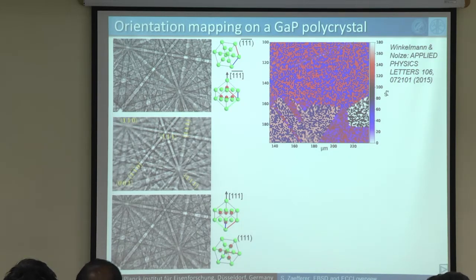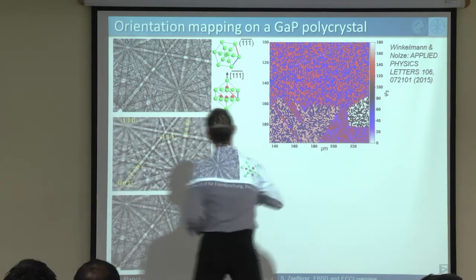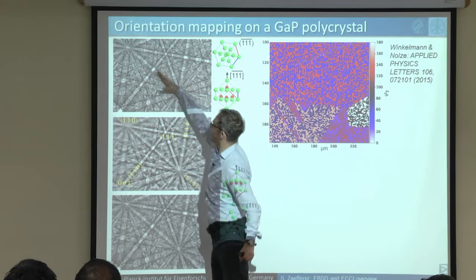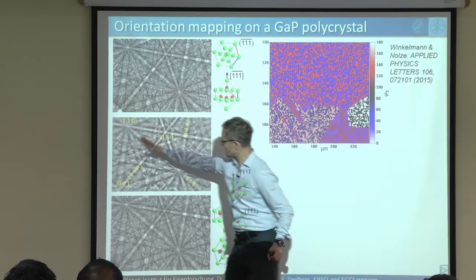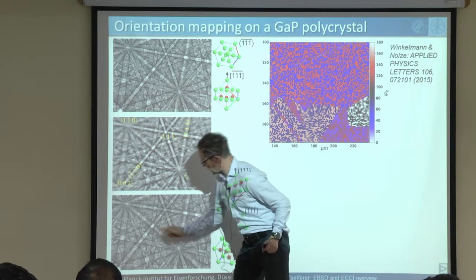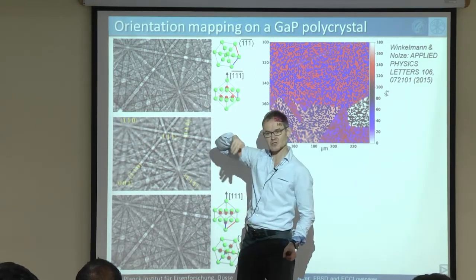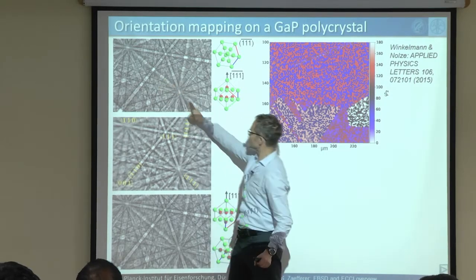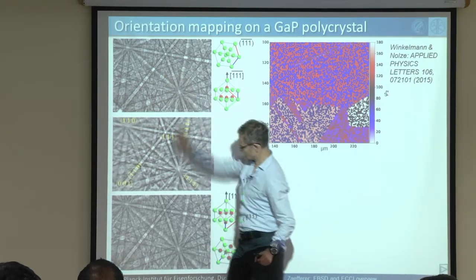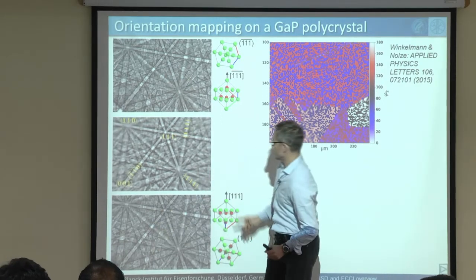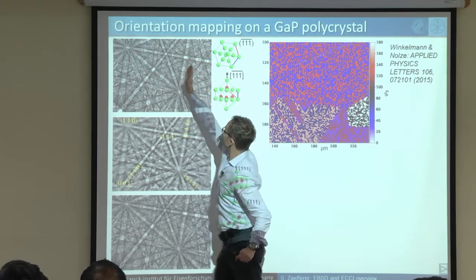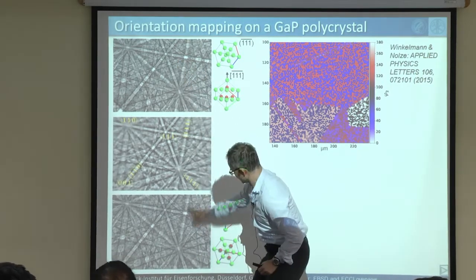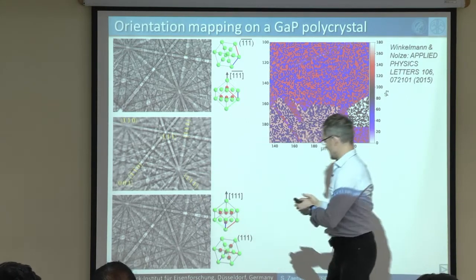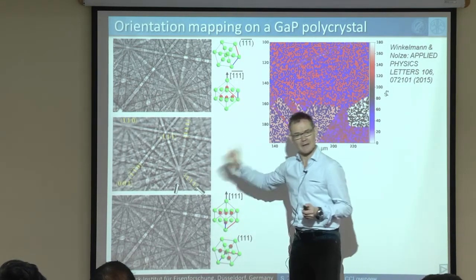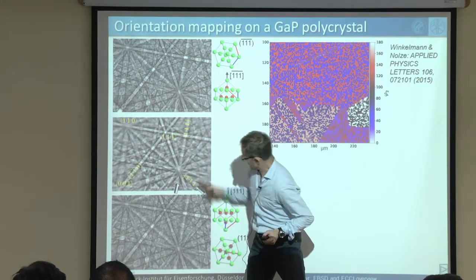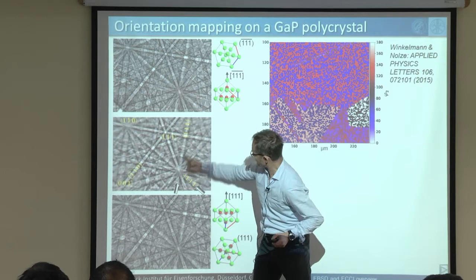And actually now you have to look very carefully. You have to look into these diffraction patterns in more detail. For example, you take this band here, which is here in the experimental, and here in the two calculated ones. And now, if you have sufficiently good eyes, you will see that the white part is a little bit on the top of the band, while here the white part is a little bit on the bottom. And there is another line, this line here. The white line is a little bit to the left, and here it's a little bit to the right. I have plotted that with more details, and you find the same thing in the experimental pattern. So here the white thing is a little bit to the bottom, and the white thing here is a little bit to the right.